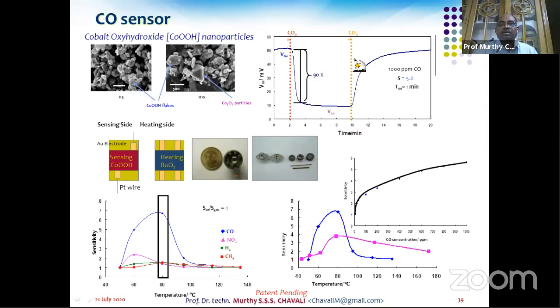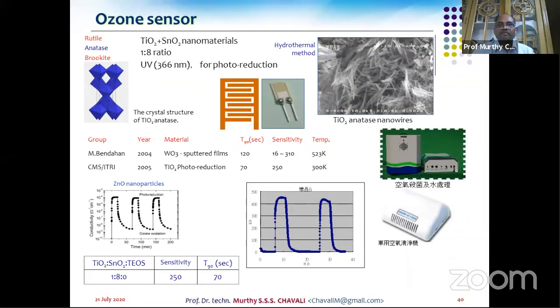We initially ended up developing it at a 500 degree temperature, but somehow we were able to succeed with a room temperature CO sensor, and this has been published, and one patent is also pending. We have very good sensor dynamics, on and off characteristics, and interference was also studied with methane, hydrogen, and other gases. Typically this material is nano cobalt oxyhydroxide prepared by the hydrothermal method. As I said, beneath you have ruthenium oxide for heating initially, and this has been removed over a period of 1 year so that we are able to have sensing at low temperatures, like room temperature.